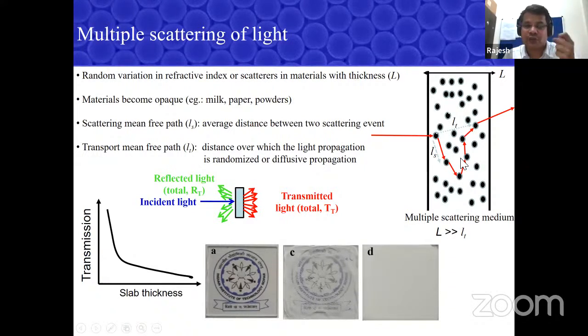So if you have a disordered sample, you take our logo, you have a plain glass plate, and on top of that you make some disordered powder or sample, you can see that its transmission is faded, so you can't see the symbol. And if I increase the disorder, you can see that it's completely opaque, like a fog. You can't see what is behind it. Okay, so this is a simple example to show you how multiple scattering happens within these white powders.